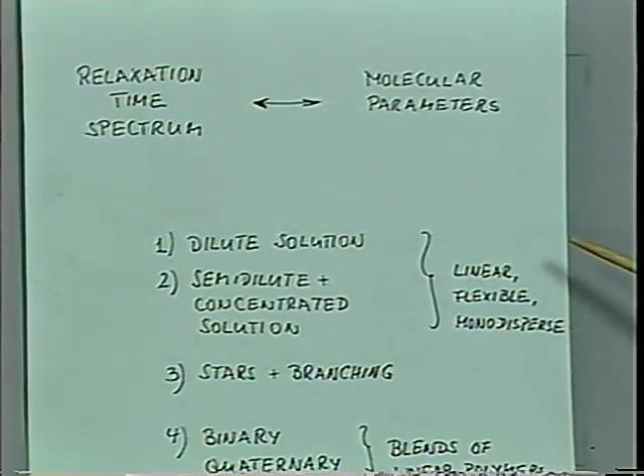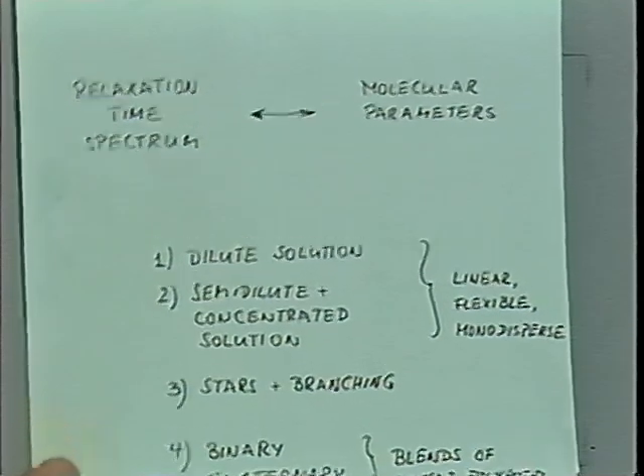Now, in the literature, you find very often that the knowledge of polymer solutions will tell you everything about polymer melts, or vice versa. And as you will see, it turns out that polymer solutions have a much more complicated relaxation spectrum than polymer melts. It's a binary system, and we will not be able to represent the relaxation of the solution in a simple fashion as you just saw before. Actually, it's a rare exception to have a spectrum like we found for the melt for the monodisperse polymer.